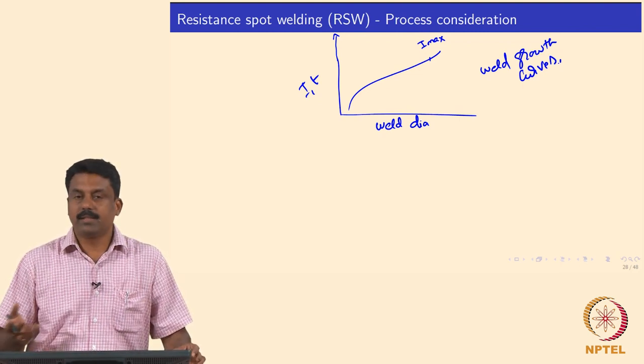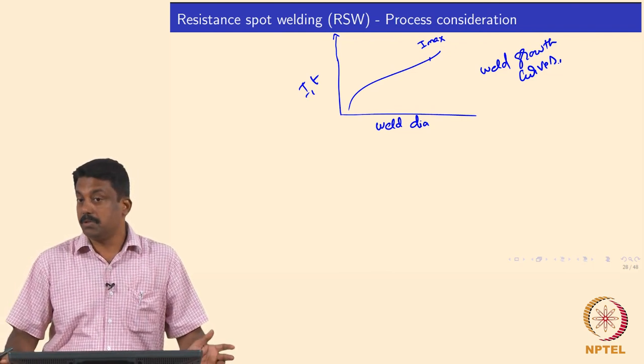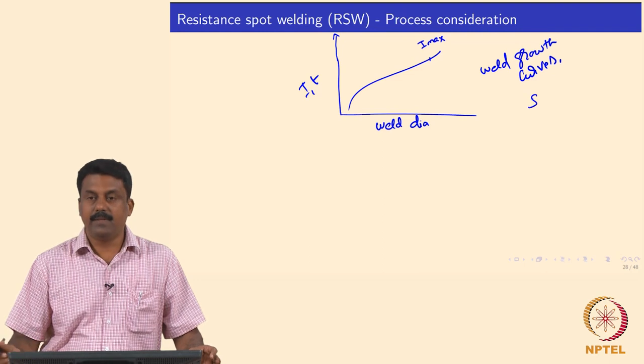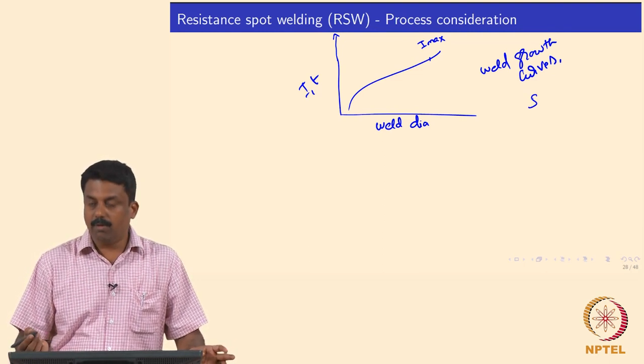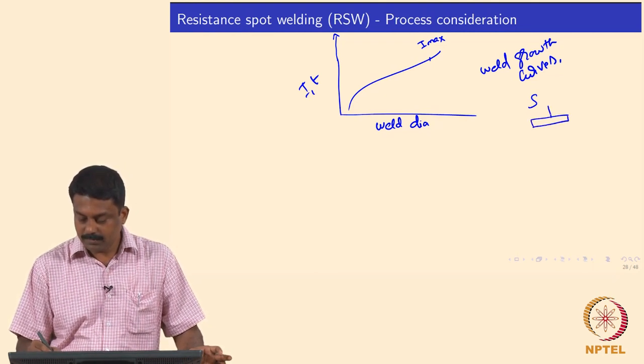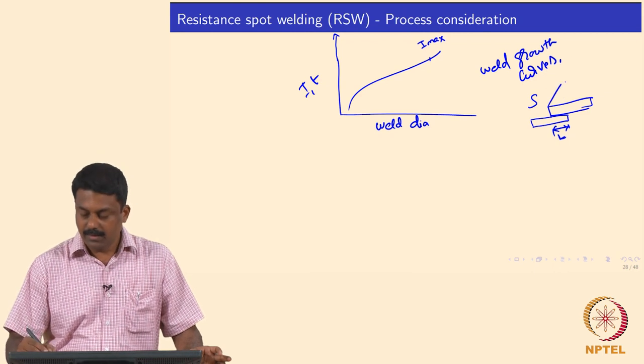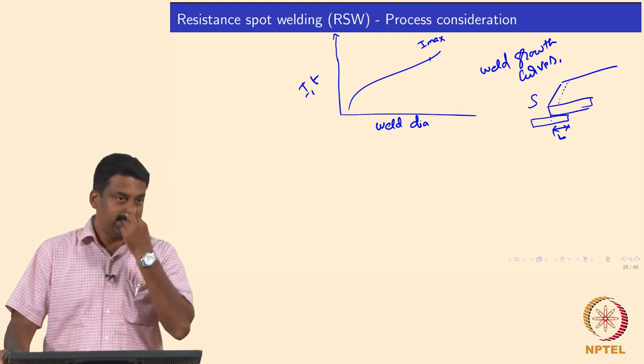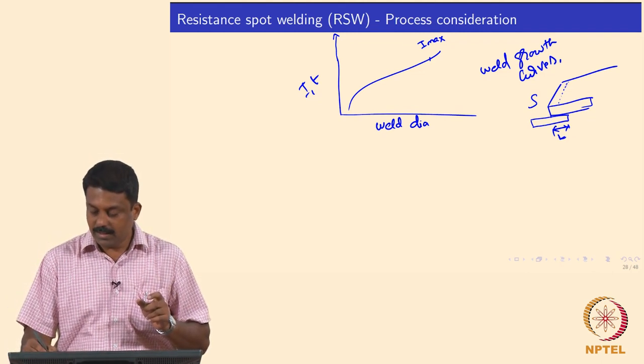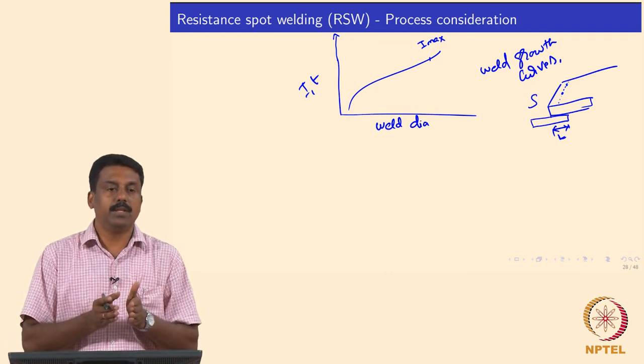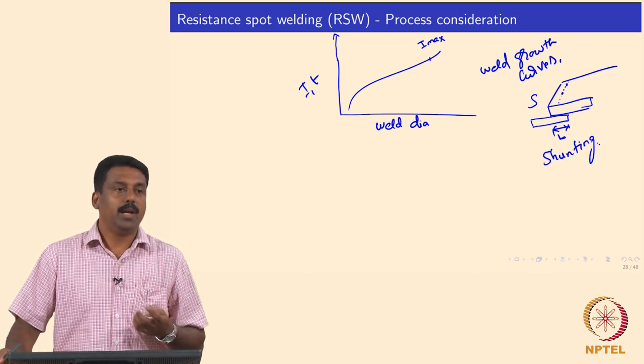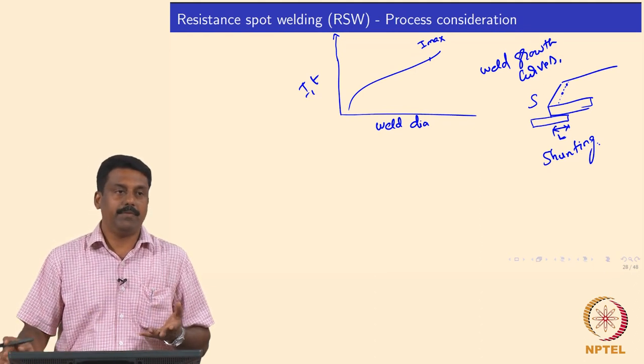We also looked at geometrical advantages and disadvantages of resistance spot welding, including the minimum distance needed between two welds. S is the distance between two welds in an overlap joint. For an overlap distance L, the weld is placed at L/2. The distance S between two welds is critical because keeping welds too close can cause shunting, which is problematic and why it is important to maintain a minimum spacing.